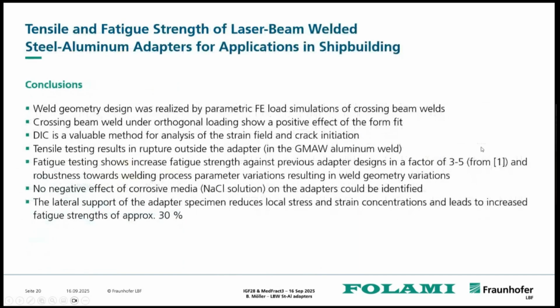And with this, I come to the conclusions of my talk. So we investigated here laser beam welded steel aluminum adapters. First, starting with a parametric FE simulation on crossing beam welds to define the weld geometry design for such an adapter. Then we investigated these crossing beam welds under orthogonal loading, which is the critical one, and showed the positive effect of this form fit of the crossing beams.